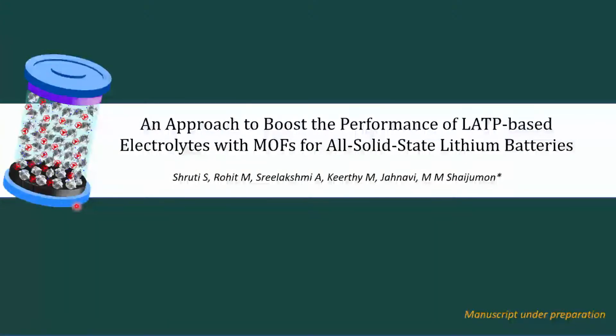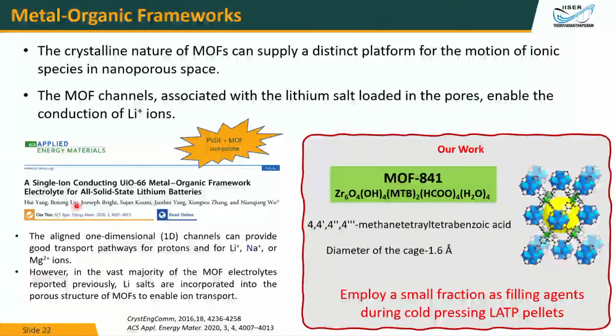How many of you have heard of MOFs? Yes, metal organic frameworks are made of a metal center with an organic ligand, and they are highly porous in structure. You can tune their pore size based on the ligand or the metal ion that you are using. So metal organic frameworks are really a promising class of candidates. What we did is, we tried to incorporate these metal organic frameworks, and we tried to avoid this high temperature sintering process. So this is a zirconium based metal organic framework, and these materials are proven to be single ion conductors like lithium, sodium, potassium, magnesium, and so on.